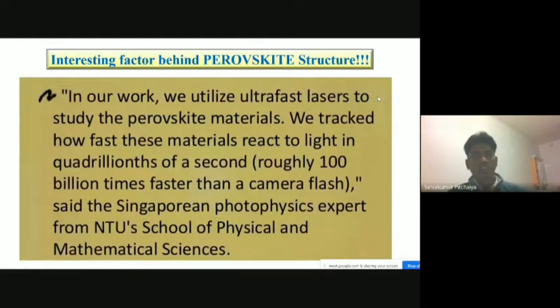One more interesting factor behind the perovskite structure is that your material has to react when it is irradiated. And according to a scientist from NTU, it reacts roughly 100 billion times faster than a camera flash. So you see how fast it can generate electricity. It can produce electron hole pairs, that is electrons and holes. It has to produce excitons. So it has the tendency to produce electron hole pairs faster.